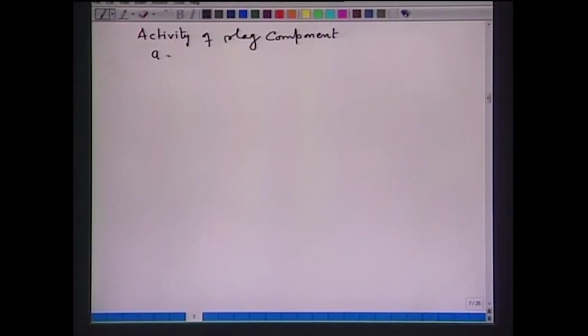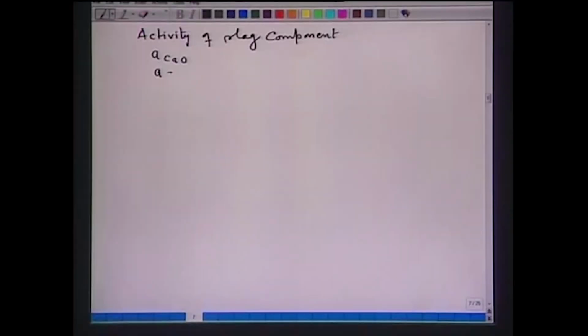Now, from a steel making point of view, we are looking at the activity of calcium oxide, because calcium oxide is a component which makes slag basic, which forms compounds with SiO2 and P2O5. So, it should remain free. Then we are also looking at the activity of FeO, because the activity of FeO determines the oxidation and reduction potential of slag. The availability of oxygen from slag to metal will depend upon the activity of FeO, that is, the free FeO content of the slag.